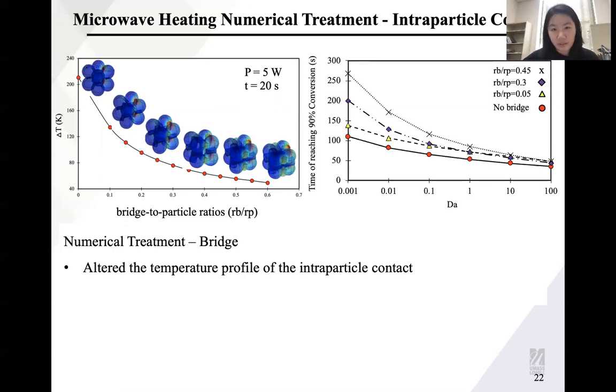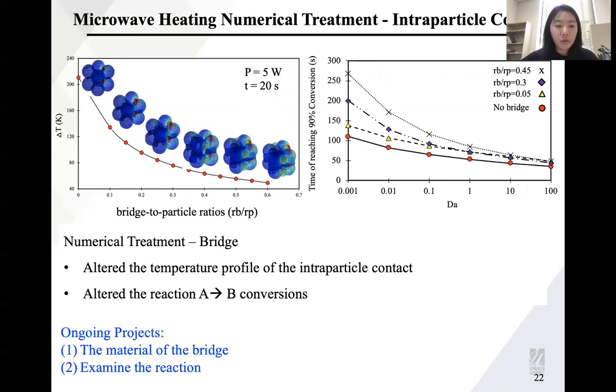And for the kinetics, we use A to B artificial kinetics, and we found that with the bridge treatment, we also alter the kinetics of A to B conversion as well. So we need to think of a better way for this numerical treatment of the bridge, how we can leverage this bridge material so that we won't change the temperature profile and at the same time we won't change the kinetics of the reactions under the microwave heating.